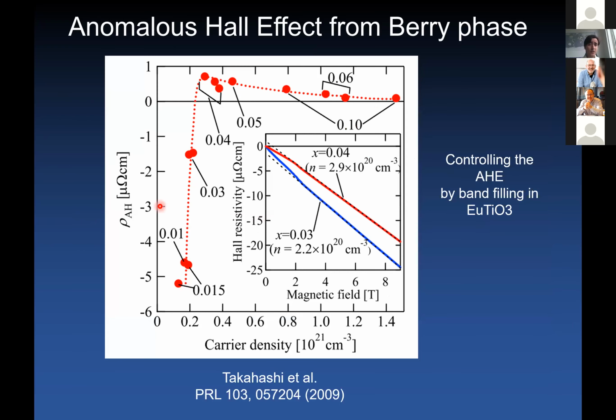And one example of observation of this type of behavior is this beautiful experiment by Kei Takahashi in 2009, where they took ferromagnetic europium titanate, and here they control the sign of the anomalous Hall effect by systematically varying the band filling. So as you move your Fermi level across this special point, which is a source of your Berry curvature, you can turn your anomalous Hall effect from being positive to being negative.